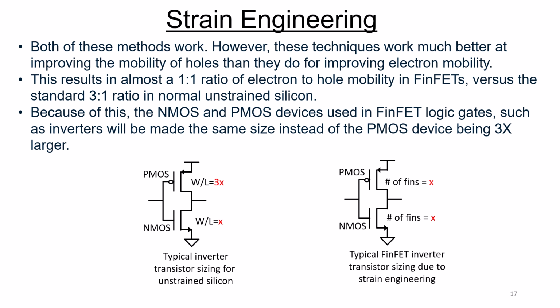So both methods work. However, these techniques work much better at improving the mobility of holes than they do for improving electron mobility. And the results are almost a 1-to-1 ratio of electron to hole mobility in FinFETs versus the standard 3-to-1 ratio in normal unstrained silicon. Because of this, the NMOS and PMOS devices used in FinFET logic gates, such as inverters, will be made the same size instead of the PMOS device being roughly 3x the size in a normal unstrained silicon process.